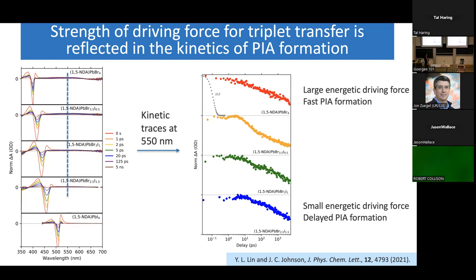All right. So what we learned from this study essentially is that both the interfacial energetics and the resulting driving force for triplet transfer affect both the luminescence outcomes in these materials, as well as the dynamics at the interface. Another thing we learned is that it's really hard to get away from this excimer formation, which makes sense because you have all these conjugated molecules that have been stuffed together in a solid state structure. So they're going to want to interact with each other.